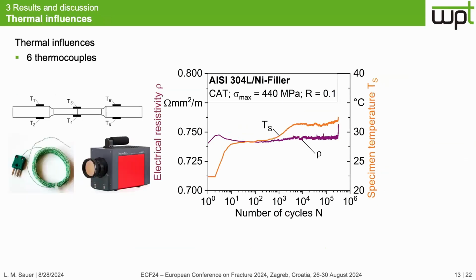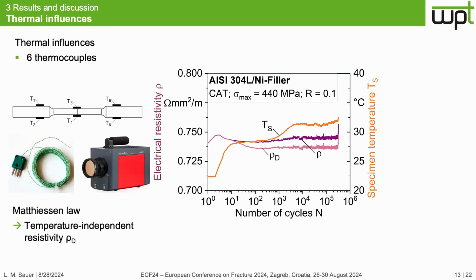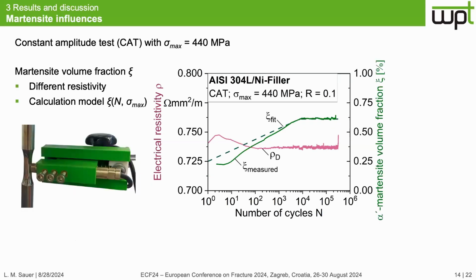And the temperature of the specimen was measured by using 6 thermocouples and, for 2 separate fatigue tests, a high-speed thermography system. And the influence of temperature on the electrical resistance was compensated by using Matthiessen's law and dividing the electrical resistivity into a temperature-independent and a temperature-dependent part. And for the following evaluation, the temperature-independent part was used.